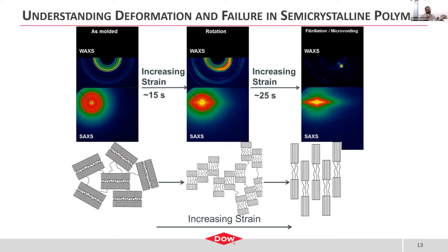Now, as you continue to strain this material and pull it to the point of failure, you start to see some really interesting features in your wide angle and small angle scattering. In the wide angle scattering, your intensity only exists in one direction. You get something that looks very much like fiber-like scattering because you are actually going through crystalline fibrillation. Secondly, in the small angle scattering, you not only get further anisotropy due to the lamellar rotation, but you actually get a sharp increase